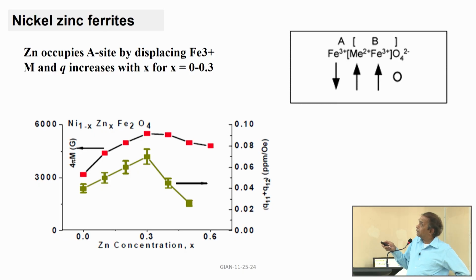And this is the structure for when I substitute zinc in some of the ferrites, for example, nickel ferrite. It has some unusual properties in the sense that zinc will prefer to go to the tetrahedral site, so it will knock some iron from tetrahedral to octahedral site. So, you can increase the magnetization for the ferrite by substituting a non-magnetic ion, and it also has a little bit higher magnetostriction and higher piezo-magnetic coefficient, but I do not want to confuse you with too many details.